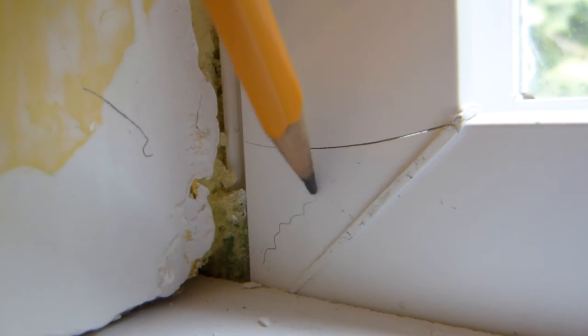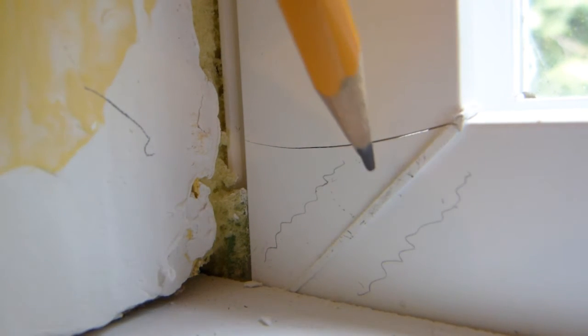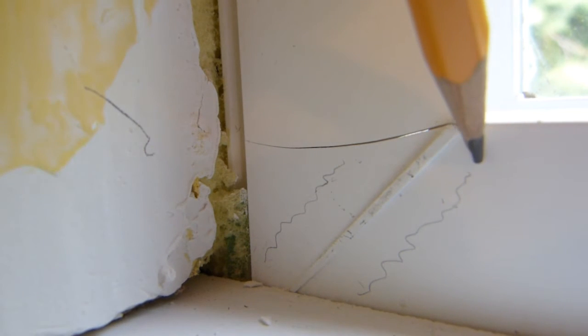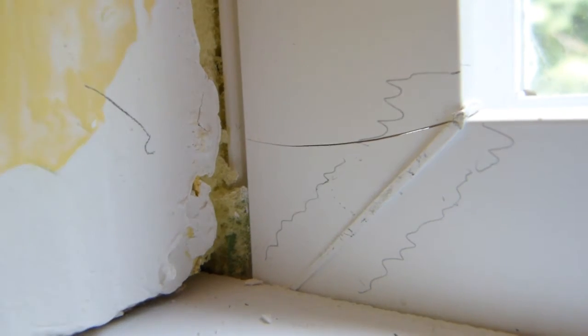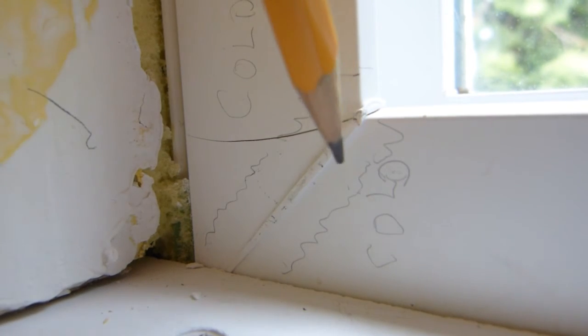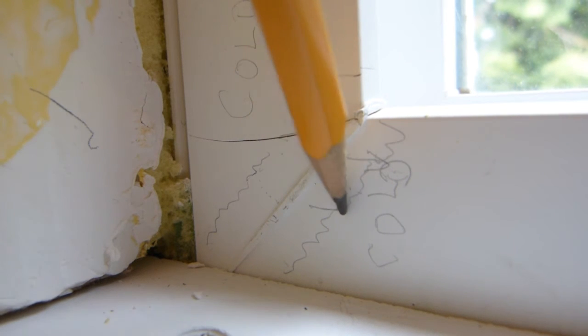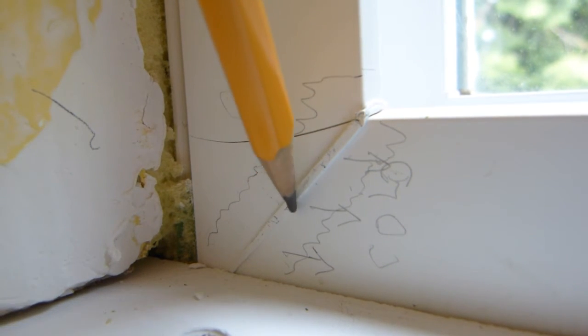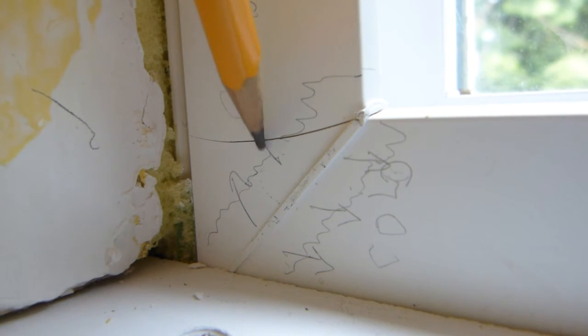So there's a heat affected zone that extends about this far out from the plastic weld there. That's the heat affected zone. Now, if this extrusion here is cold, and this one is also cold, these cold surfaces act as a heat sink and they wick away heat rapidly from this hot seam here. In this direction they wick away heat. Now, at this corner, this part seems to cool the fastest, as evidenced by this crack. That's why this crack is widest at the corner here.